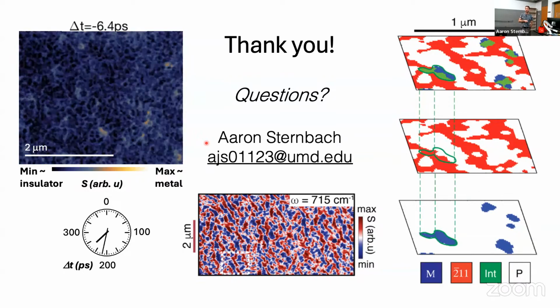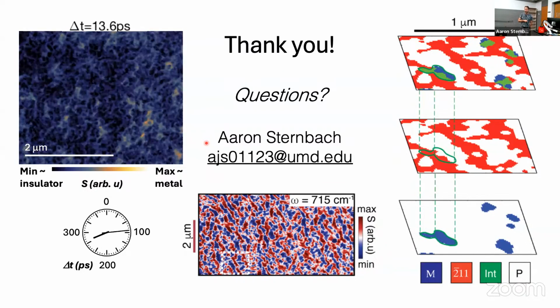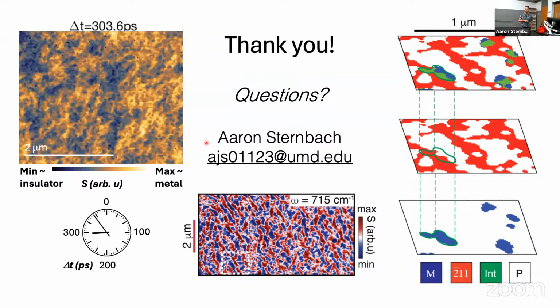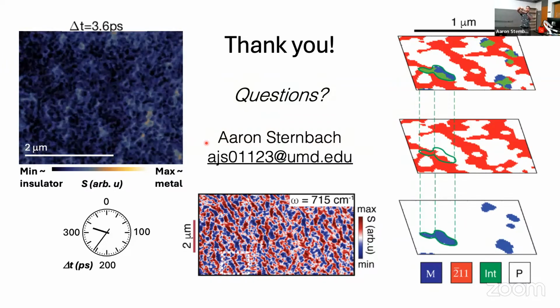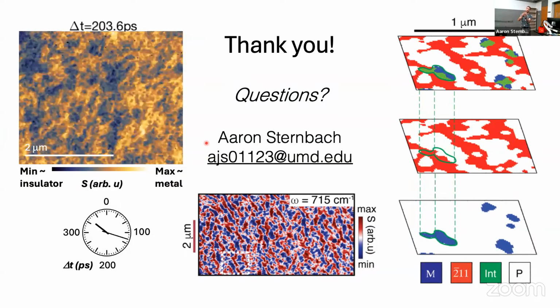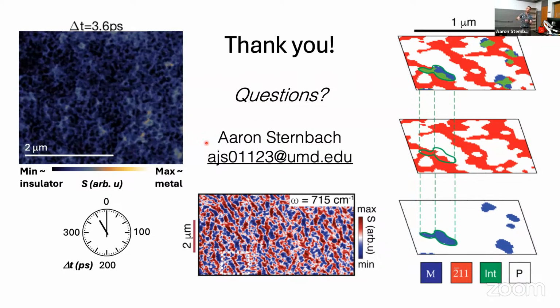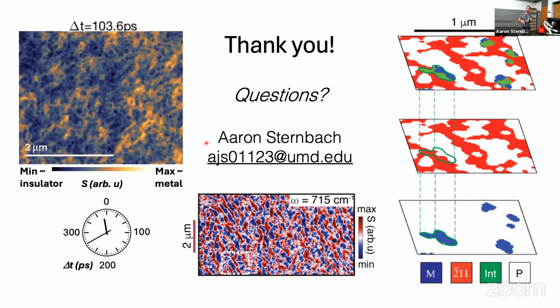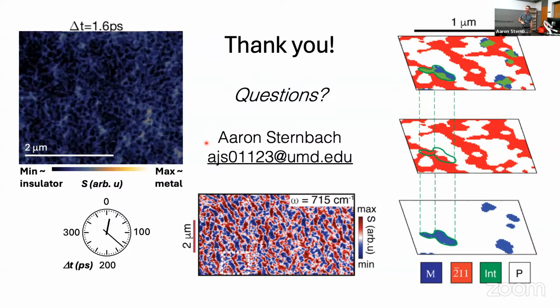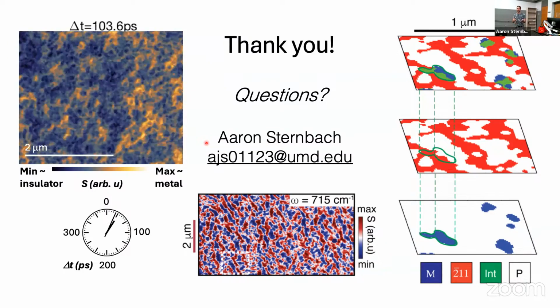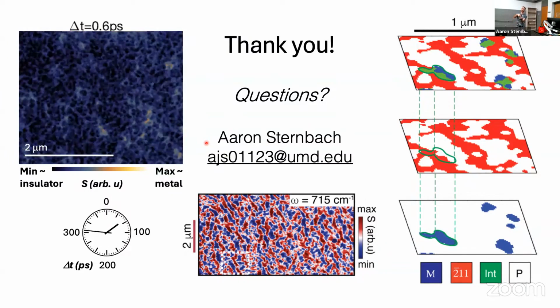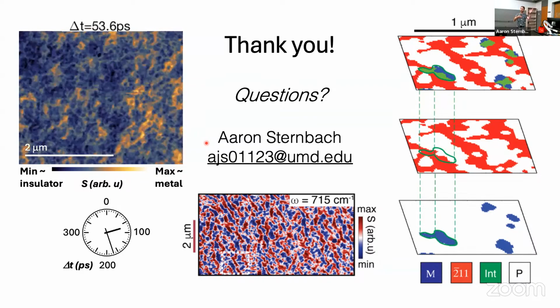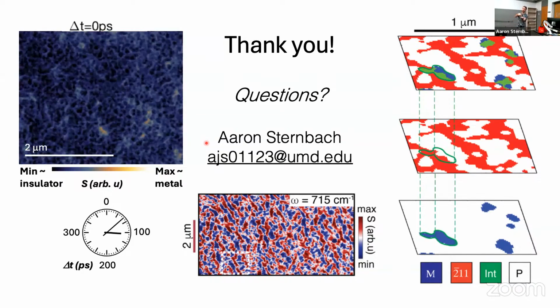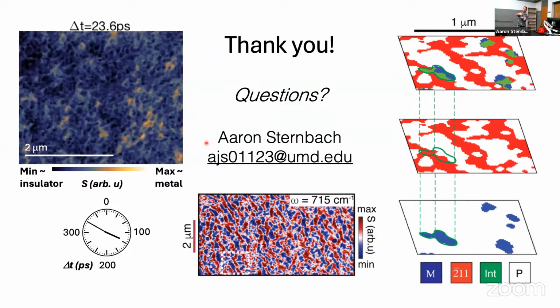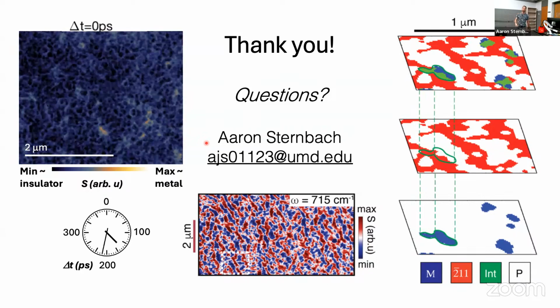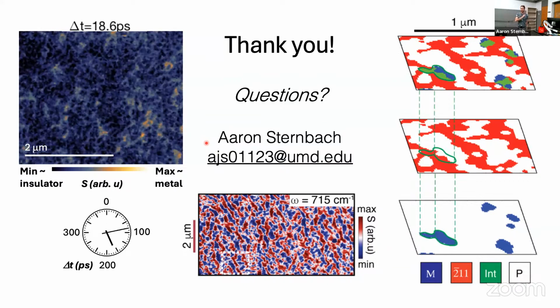And so to create this, you would have to place the tip at all these different places. No, the sample is what is raster scanned. What happens is you focus the light onto the tip, you align a detector in the far field, and if you'd like to learn that alignment procedure, maybe that would be a better conversation for an in-lab visit. I'd be happy to show you. You align it once, then you align your pump and you look to maximize this change in near field amplitude, and then everything is fixed. The tip stays in the exact same location. What's raster scanned is the sample. So you change the location of the sample under the tip, leaving the optics and the tip in the same location.